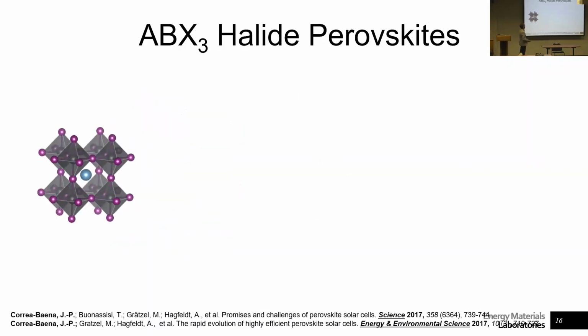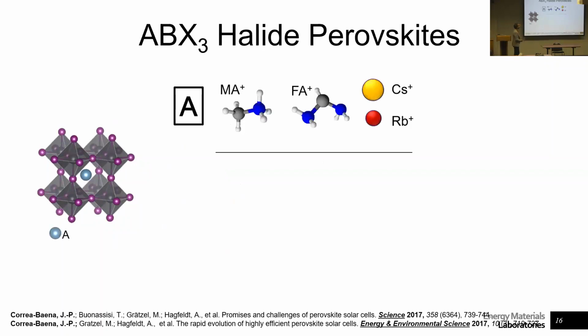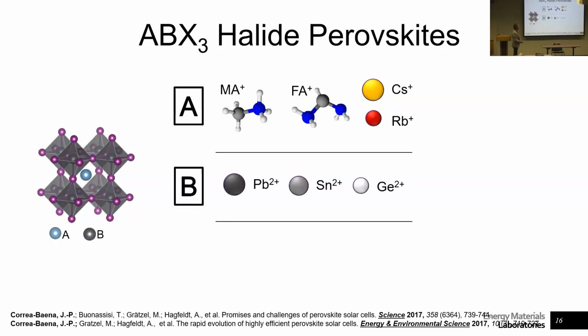So the general types of materials that we're interested in are halide perovskites, in which case we have the A site, which is that guy sitting here in the middle, which can be an organic cation, so that's methylammonium, carbon and a nitrogen, or formamidinium, where we have 1 carbon, 2 nitrogens with the resonant bonds there. Or we can have the inorganic version of those, like cesium, which has to be a 1+ charged state, or rubidium.